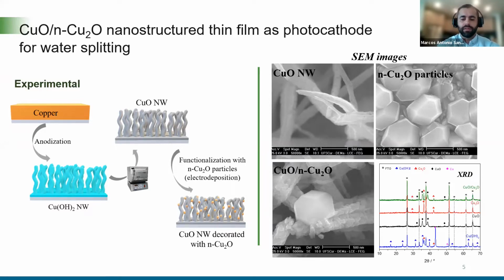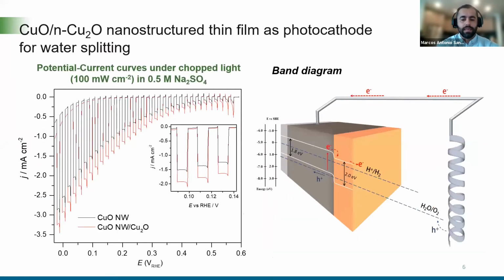So the photocathodes of copper oxide nanowires decorated with cuprous oxide presented a higher photocurrent. We notice an increase of almost 0.5 milliamperes per square centimeter. And we believe that the reason is because when we add the nanoparticles of cuprous oxide on the cupric oxide nanowires, we form a heterojunction. It brings the minimum of the conduction band closer to the redox potential. And it also can improve the charge separation, consequently improving the reduction reaction. And it's clear the positive effect of the addition of the cuprous oxide nanoparticles. And in future, we're going to study the effect of the concentration of these nanoparticles on the cupric oxide nanowires film to determine the best conditions for water reduction.